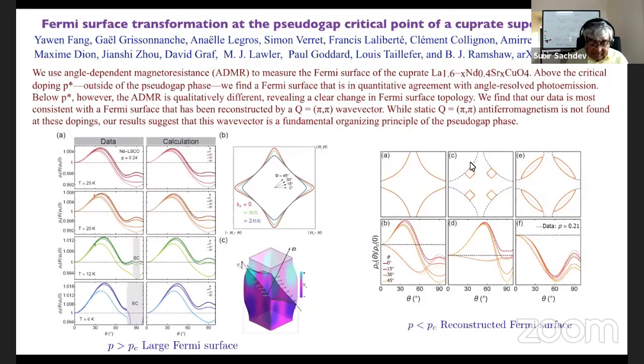So this is just as a reminder, an angle dependent magnetoresistance experiment from Brad Ramshaw and his group. And what they see after some analysis, which I won't review today, they conclude that very likely the underdoped metal has Fermi surfaces of the shape of these hole pockets, whereas the overdoped metal has a large Fermi surface. Now, this large Fermi surface is exactly what you expect from Fermi liquid theory, so things are in excellent shape here. And this small Fermi surface is something you might expect in the presence of magnetic order, but it's also clear that there is no appreciable or significant magnetic order in these materials at these dopings. So that's one of the big puzzles. Why is the Fermi surface small even without magnetic order? As they say, antiferromagnetism is not found at these dopings, but the reconstruction associated with antiferromagnetism is still somehow happening.